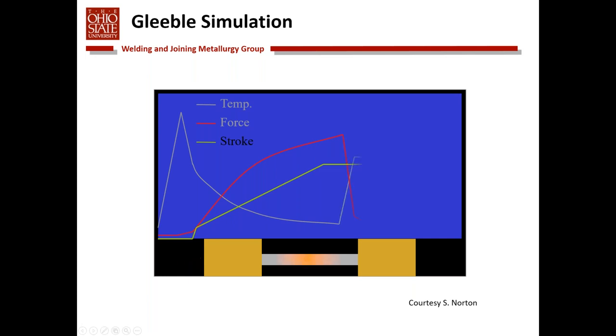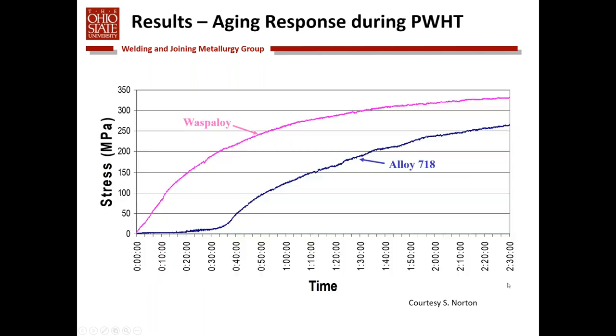We're then going to perform a post-weld heat treatment, and so we take and we heat that material to the temperature of interest and hold it for a given time. What happens to the force or the load is that it initially drops due to relaxation and then will increase, at least in nickel-based alloys, due to the onset of precipitation.